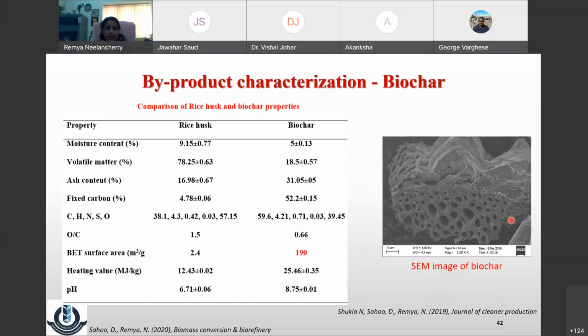And further, if you see the characteristics of this rice husk and the biochar, the moisture content, because in rice husk itself the moisture content is very less, it's almost a dry product. Volatile matter content is converted to fixed carbon. So its volatile matter content is completely reduced, and you can see the corresponding increase in the fixed carbon from 4.78 to 52.2%. Tremendous improvement in the carbon, decrease in the oxygen, and high improvement in the BET surface area and heating value. Right?